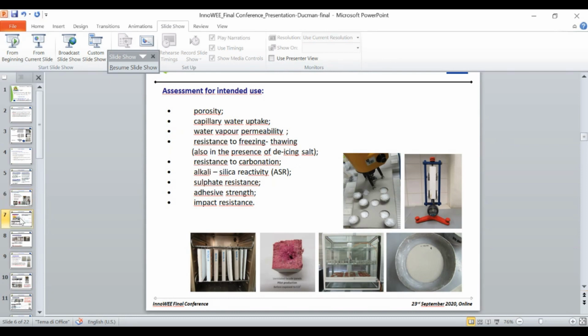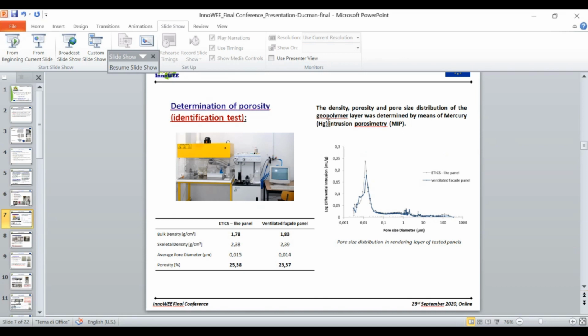So the first one is more like an identification test. It's not required in any of these standards, but this is a fast test method, which gives information about density, porosity, and pore size distribution. And as such, it can serve as an identification test to compare different samples with each other. Here you can see the results for two types of panels, the ETICS-like panel and ventilated facade panels. What we can see is that the results are pretty similar. The composition is the same for both types of panels. The production technology you have seen just before is similar. So we also expected that these values will be pretty similar for both of the panels.